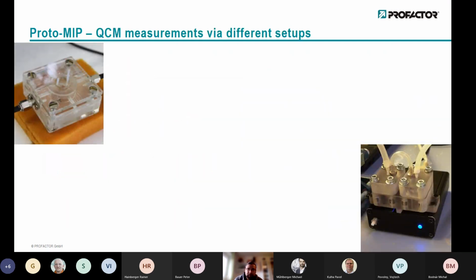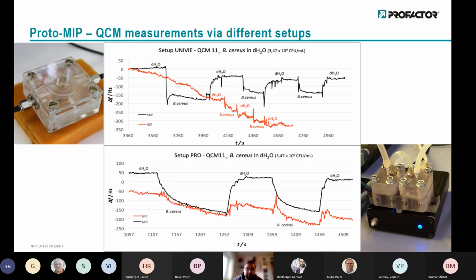And in that way, what we achieved is one of some examples of such a measurement curve. We saw QCM measurement before also, but let me guide you through it. What you see here, I hope you can see my mouse, is that you start with water as matrix solution, and here you introduce through these pipes. In this case, this was done by University of Vienna, which is a partner in this project. On their setup, which is not comparable and comparable at the same time, you introduce the Bacillus cereus solution and you have a frequency shift. This frequency shift is proportional to the mass loading on the QCM, which gives then a frequency drop. So the higher the frequency drop is, the lower the frequency is, therefore you get a better signal.